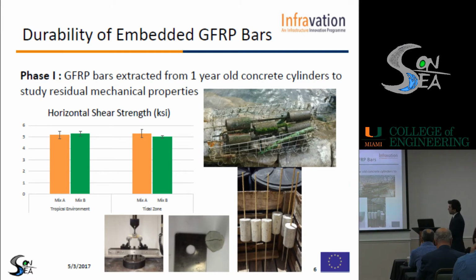And then, as you can see in the graph, these are the results after 1 year. So we went there, and we extracted the bar after a year. You can see mix A, which is conventional concrete, and mix B, which is your seawater concrete. After a year in tropical environment, we actually got higher results for our embedded bars in mix B, which is seawater concrete. And then you go to the tidal zone.